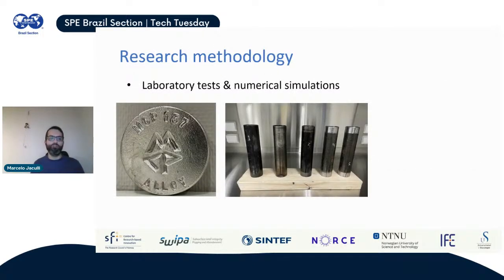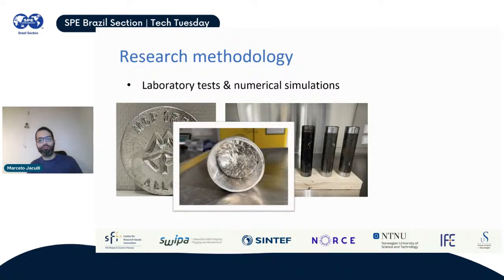So here, just for curiosity, we have some pictures from the lab. That's the test that we have been running. You have some pipe samples that were provided to us. And here you have the alloy that we buy from a manufacturer, which is the eutectic bismuth tin alloy. And you can see here the 137 is the melting point. Then we melt this, pour it into the pipe, let it solidify, and you create a plug like this. So that's basically the idea.